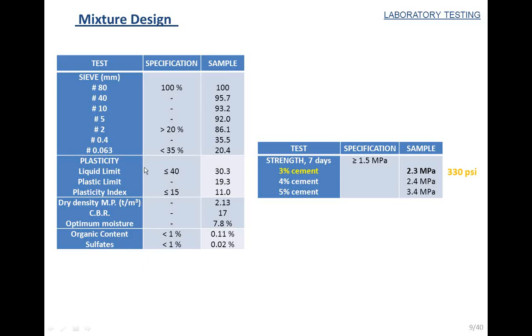So the first thing is selecting the soil, and then the next step is adding different quantities of cement and testing for compressive strength. And the Spanish specification establishes 1.5 megapascal for the compressive strength. So in this case, just with 3% cement, which is the minimum content according to the Spanish normative, we could have a compressive strength which was over 1.5 megapascal. So this was the compressive strength that we were obtaining after 7 days for this material.